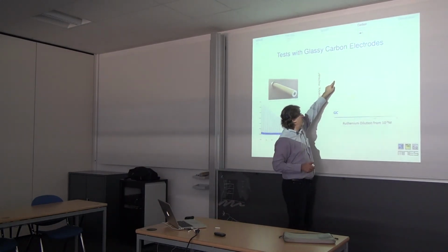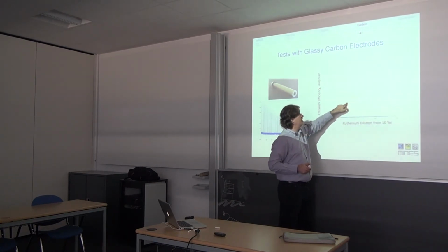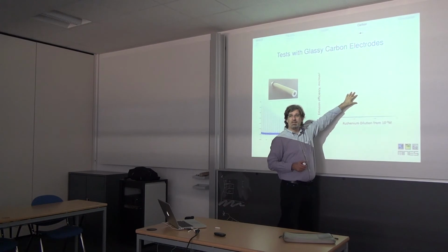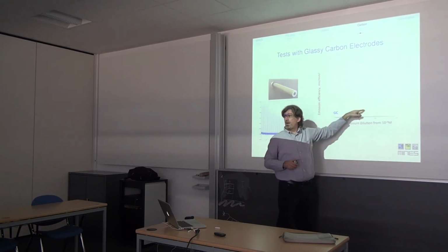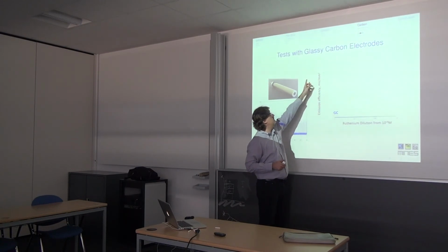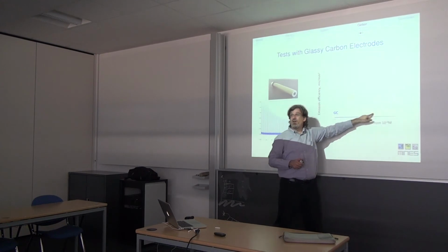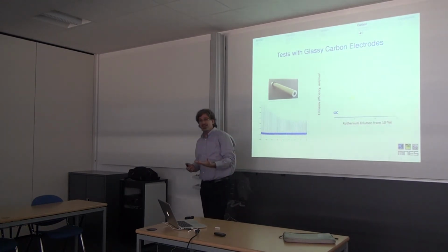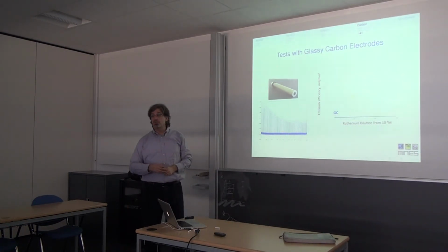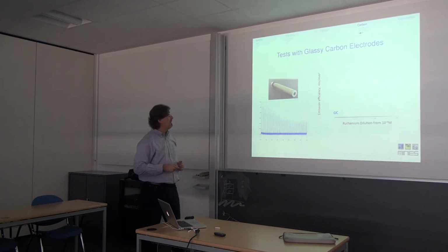But look at it. This is the efficiency in terms of emission of, sorry, it's yellowish, you don't read it very well, of a carbon nanotube. And this is the emission, again, in millivolt on millimeter square of a glassy carbon. The efficiency of emission of the glassy carbon is absolutely nothing in comparison to the one of carbon nanotubes.